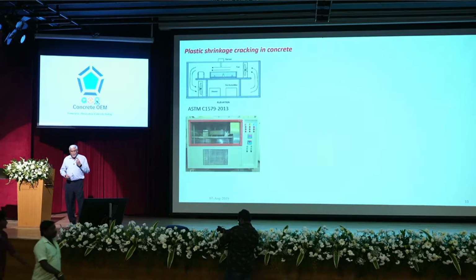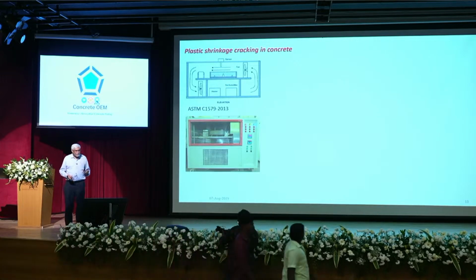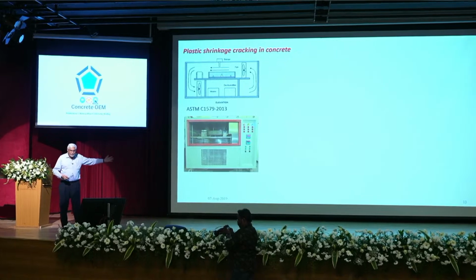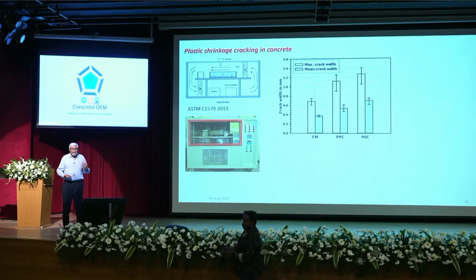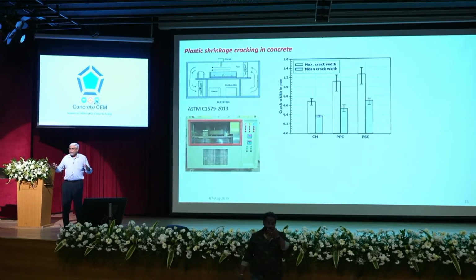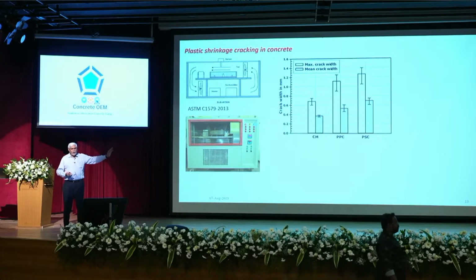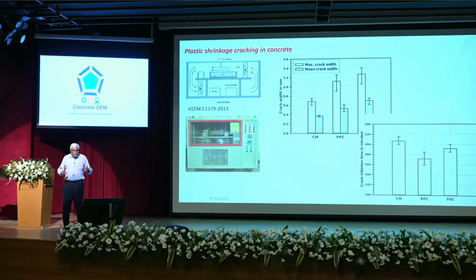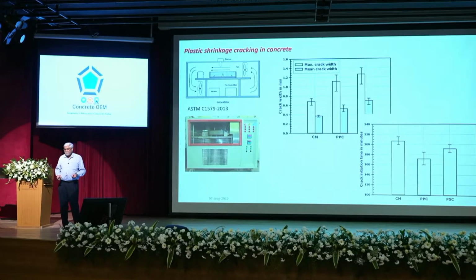And there we can understand what is the problem and think of what is the cure for it. Plastic shrinkage cracking is becoming very, very important, not only because of our climate, but we are using more cement, we are using cement that gains strength slowly. So one of the things that we have done in our labs is look at slabs of concrete, different types of concrete. We blast it with hot air and see how it cracks. And we find that if you compare ordinary Portland cement with concrete made with PPC and PSC, PPC will crack earlier if you do not cure it. It will also have larger crack widths.